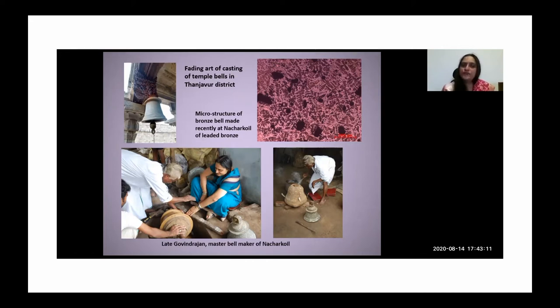And I had taken you through the stages where first the mold is made on an axle, and then the wax model is applied on top of it, and then it's encased in layers of clay to form the mold, and then the metal is poured in to get the shape of this bell. And at the top there, what you're looking at is the microstructure of this Nacharkoil temple bell. So now you can see that that's quite different from what you've seen in those beta bronzes. You're seeing that dendritic alpha phase over here, and you're also seeing a lot of the alpha plus delta eutectoid, which would not have formed had it been quenched and so on. And you're seeing a lot of the lead also, which is globular lead. So this is a leaded higher-tin bronze. This has about 18% tin and about 5 to 7% lead.